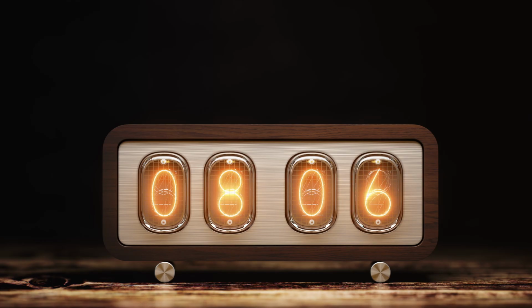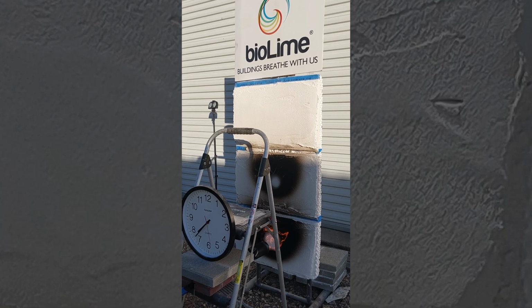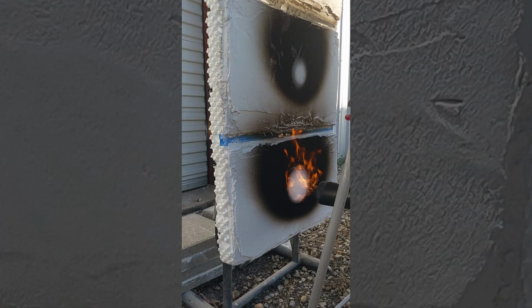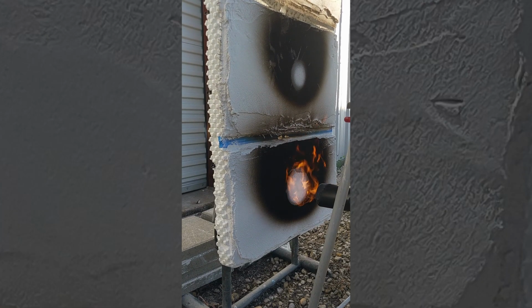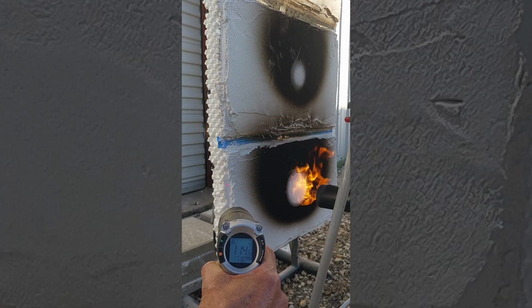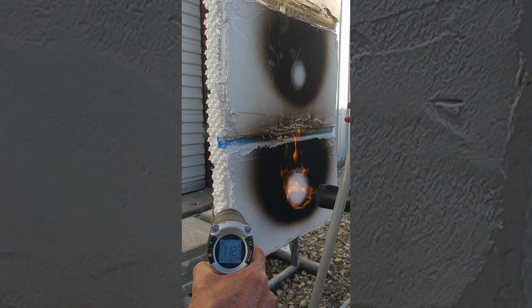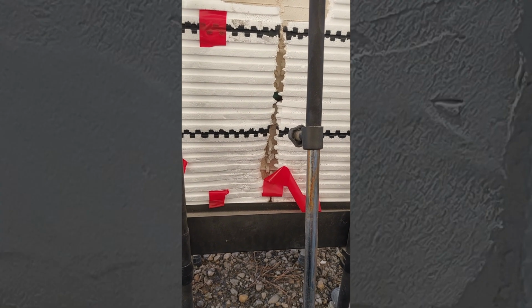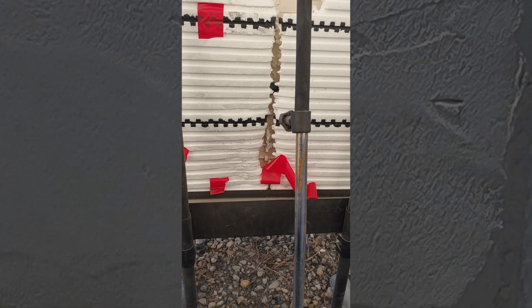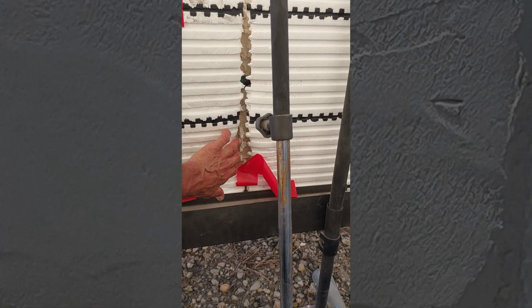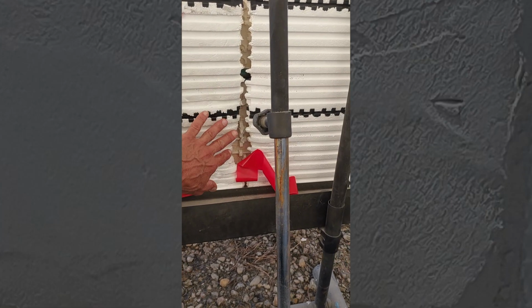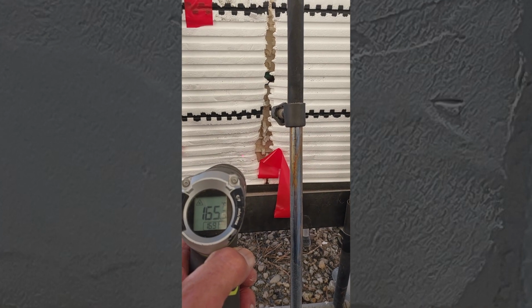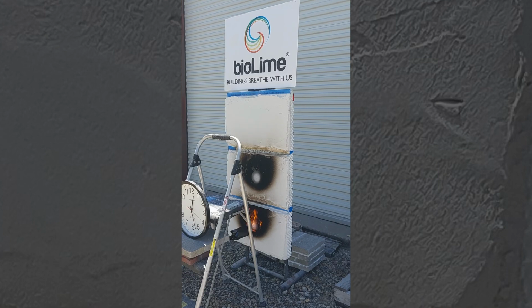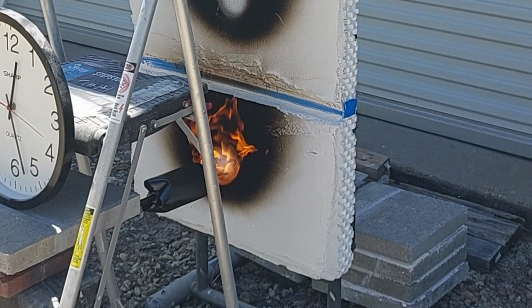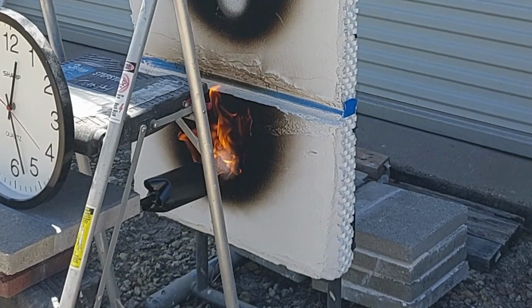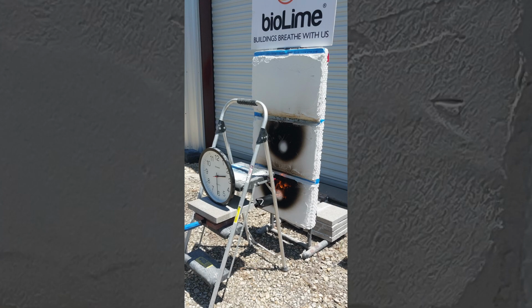For the final observation at the 8th hour, we see the BioLime coating is still fully intact and bonded, no signs of delamination, and as we move to the outer edge of the test area, temperature readings are around 120 degrees. On the back side, the ICF styrofoam is only slightly deformed, however, it's not melted or pulled away. The red tape hasn't burned either, and temperature readings are consistent with what we've seen throughout the day. Given the fact that for the full 8 hours, we've had a flame burning at over 2000 degrees Fahrenheit directed at the front of our setup, this is an amazing result.